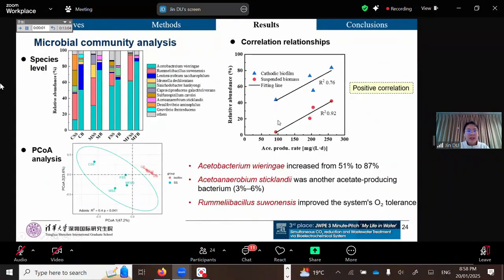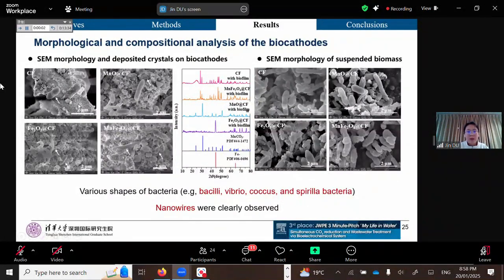The microbe community analysis supported the observed reactor performance results. It showed that in the manganese ferrite modified group, Acetobacterium accounted for 87% of the relative abundance in the cathode biofilm, significantly higher than the 51% observed with the unmodified electrodes. This increase is likely due to the enhanced electrochemical activity, larger surface area, and improved biocompatibility of the manganese ferrite. The SEM images reveal diverse morphologies having direct contact with the cathode. The nanowires resembling conductive pili were clearly observed, suggesting potential direct electron transfer from the cathode to the electroactive microorganisms.